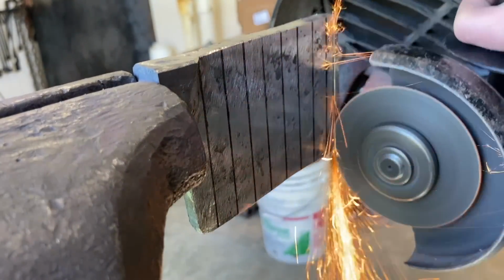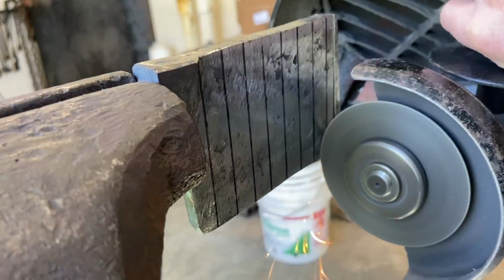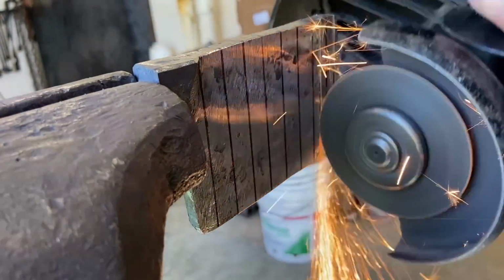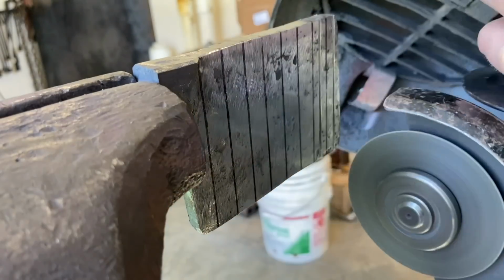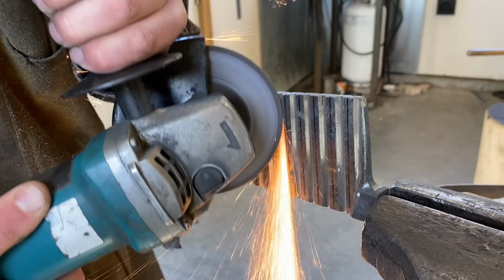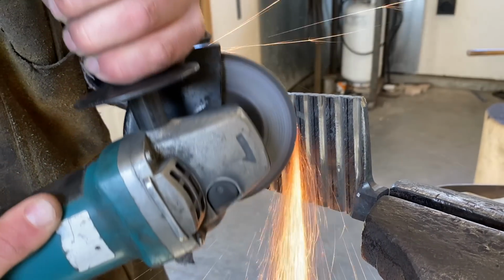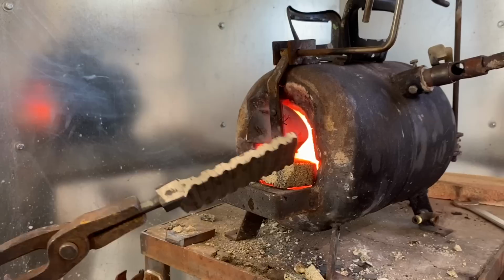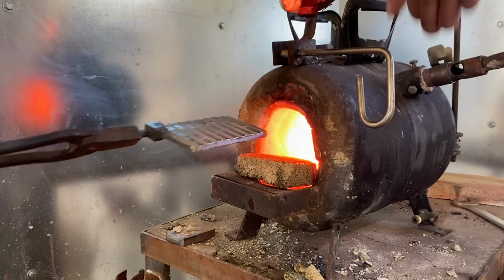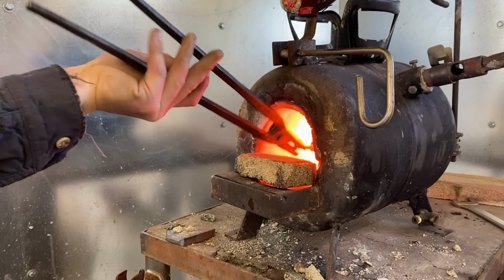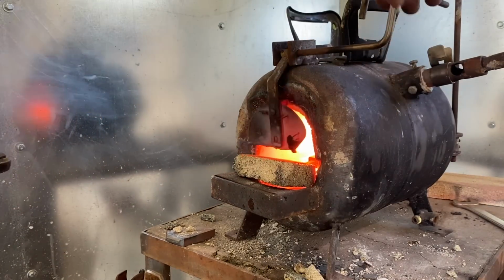I grind grooves into both sides of this knife preform with the angle grinder. The grooves are staggered side to side, making it look kind of like a crinkled potato chip. When I flatten out that wiggly blade, the straight layers internal to the steel then assume the wiggly formation, which will be revealed as soon as the blade is finished and etched.